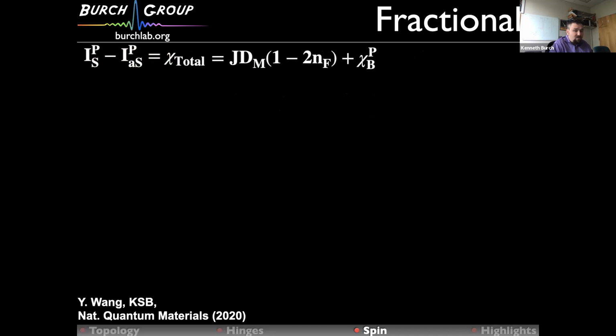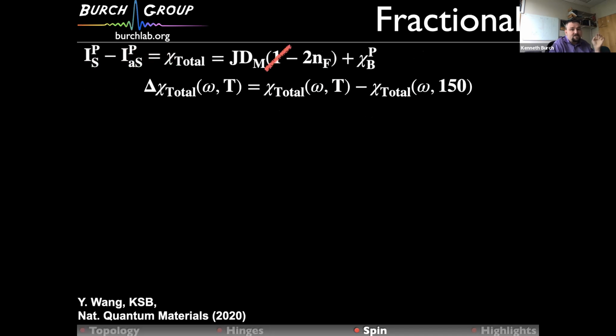And then furthermore, we wanted to really focus on its temperature and energy dependence to look for this fermionic statistics. And so we wanted to get rid of this 1. So what we did was we went to a temperature where we knew that basically there was no temperature dependence coming from magnetism, and even the phonons were basically boring, which turns out to be about 150 Kelvin. But for the results I'm going to show you, it almost didn't matter. We could choose anything between 100 and 200 and get the same.